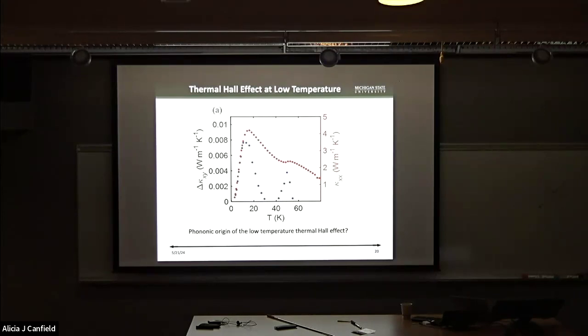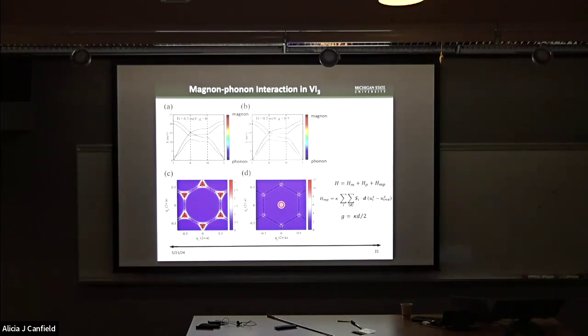So how does the phonon play a role here? As I just mentioned a minute ago, this system shows a strong magnon phonon scattering. Therefore, our theory collaborator did some phonon calculations by taking into account the magnon phonon scattering. The top two figures show both the phonon and magnon dispersions with and without considering the magnon phonon coupling. The blue curves are the phonon bands, the red curves are the magnon bands. So we can see that if we take into account the magnon phonon coupling, the magnon and phonon bands will hybridize. For instance, if I zoom in on the low energy one, you can see that the magnon and phonon bands anti-cross each other and hybridize.